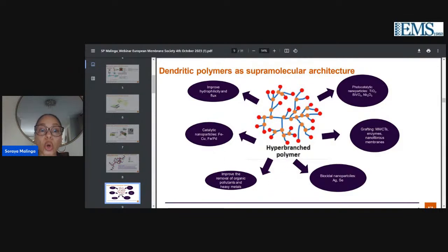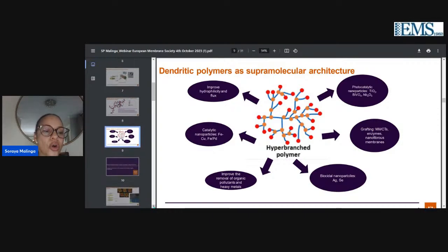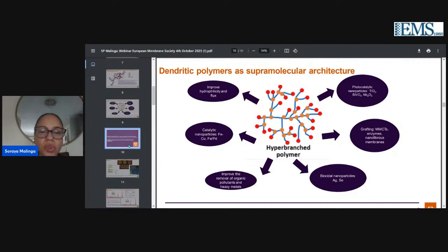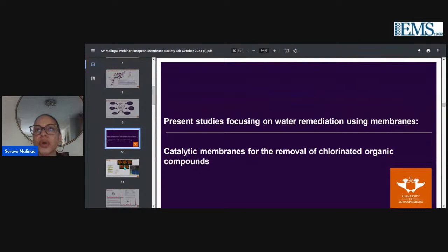We have then explored the use of this hyperbranched polymer to improve hydrophilicity and flux, and catalytic, where we've prepared catalytic particles, as you'll see in the next slides. We've used it to improve the removal of organic pollutants and heavy metals, and also to prepare photocatalytic nanoparticles. We've grafted different molecules such as multi-walled carbon nanotubes, enzymes, and nanofibrous membranes, and we've also prepared biocidal particles such as silver and selenium that are targeted for removal of bacteria.